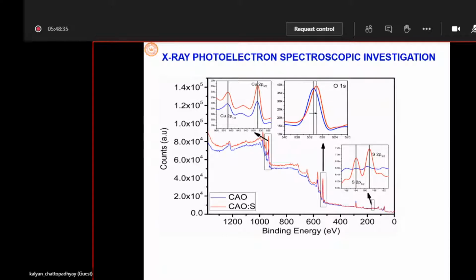about, initially he stated some basics of photoelectron spectroscopy. Now, I just mentioned that here, for example, the blue line is the pristine copper aluminum oxide, XPS of the surface, and this is when the oxygen was incorporated in the anionic site. And see, as soon as the sulfur incorporated sample was introduced, you see the sulfur peak, which is 2p 1/2 and 2p 3/2.